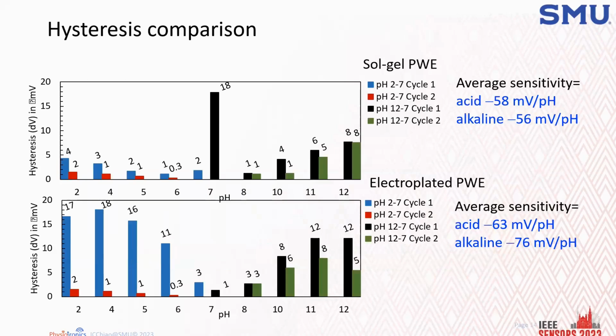So to compare electroplated with sol-gel, these are 2 main takeaway points. For sol-gel, the sensitivity between acid and alkaline is roughly the same. And for the electroplated one, the sensitivity is better than the sol-gel electrode. However, you can just see the bar here. You can understand that the hysteresis is worse for the electroplated one. And we do believe that's because the surface state got modified in the solution.